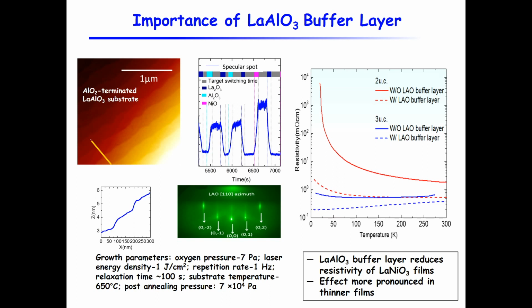So these are color coded for all these different layers. We grow lanthanum aluminate until this intensity oscillation becomes very nice, and then we start to put the first layer of nickel oxide. And we found that that's important.